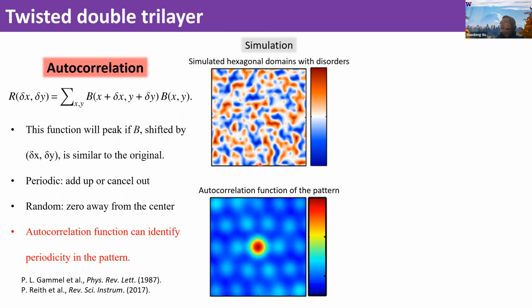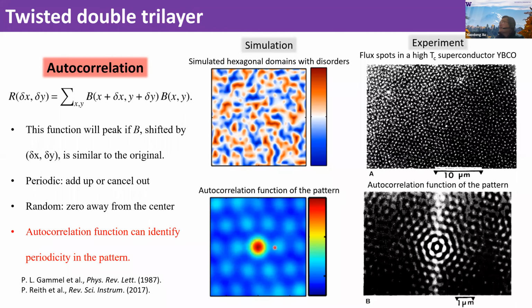This technique has been used in the past to extract magnetization information. For example, this is data we took from this paper, where they simulate these hexagonal domains with disorder. This is the hexagonal magnetic order, and they add disorder. Once they do this autocorrelation, you can reconstruct the hexagonal pattern of magnetic domains. And this is another example, which measures the magnetic flux in a high-Tc superconductor, YBCO. They also do this autocorrelation function and reconstruct these magnetic patterns in the structures.